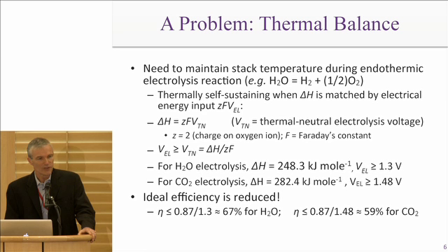So the delta H for the reaction is basically proportional to the voltage that you're operating the device at. And z and F here are just constants, the Faraday constant and the charge on the ion in the device. And so this voltage here represents what we call thermal neutral voltage. So you're putting in enough electrical energy to compensate for the thermal energy requirement of the chemical reaction. Okay? And so the electrolysis voltage then should be higher than thermal neutral voltage given by this. For steam electrolysis with this reaction enthalpy, it turns out you need to be above 1.3 volts. If you're doing CO2 electrolysis, you actually need to be above about 1.5 volts.